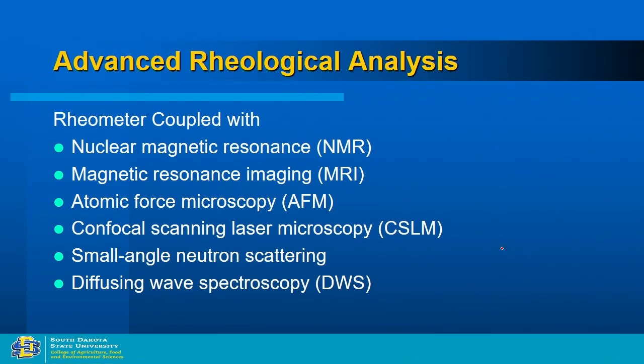So what are the advanced rheological analyses? Typically, when the rheometer is coupled with nuclear magnetic resonance, magnetic resonance imaging, atomic force microscopy, confocal scanning laser microscopy, small angle neutron scattering, diffusing wave spectroscopies. So these are all the opportunities available. If there is a way they can couple the rheometer with this new way of looking at things, then we can take these rheological measurements to the next level. So that kind of opportunity is available there, but a lot more work needs to be done in that area.